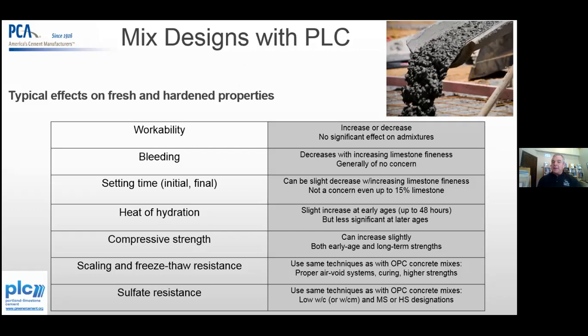Compressive strength, it's all within the variability of the test method itself. Although the slide says can increase slightly both early and long-term strengths, it's comparable. We found comparable performance. We've had some guys who say, oh, it's a little bit less, and we've had other people say, well, it's way better. But on par for all the testing that we've seen, it's one for one. It's a direct replacement. Freeze-thaw resistance, you have a good air void system, good water cement ratio, it's not a problem. And sulfate resistance,